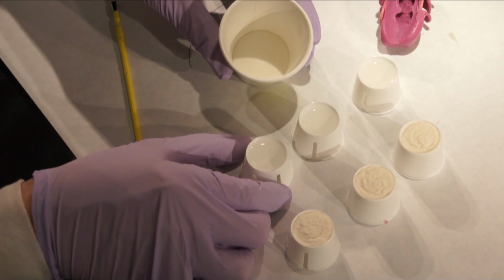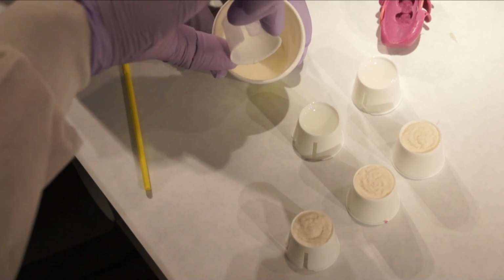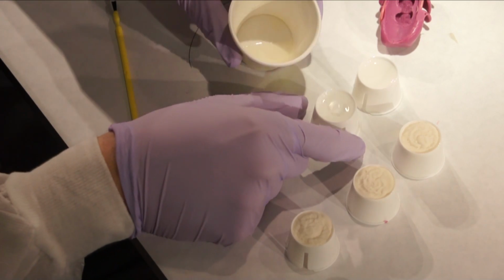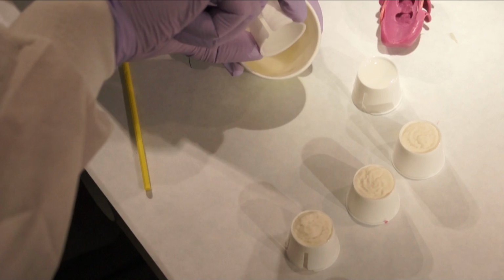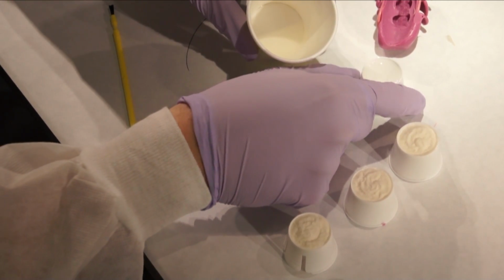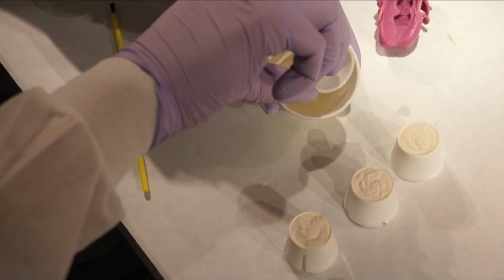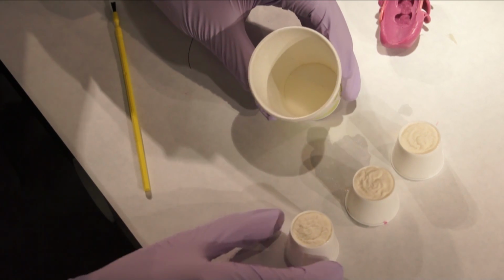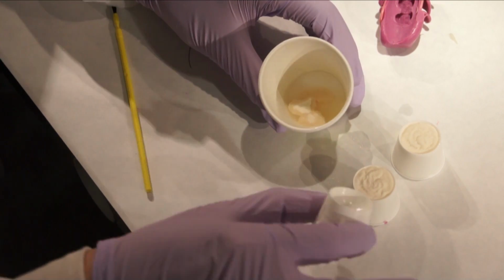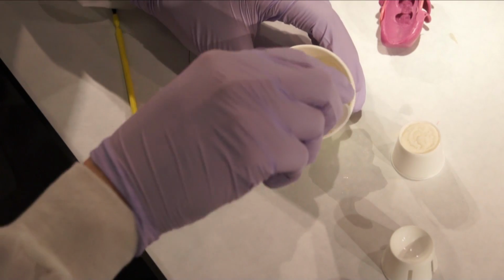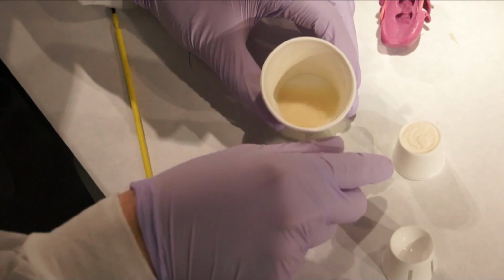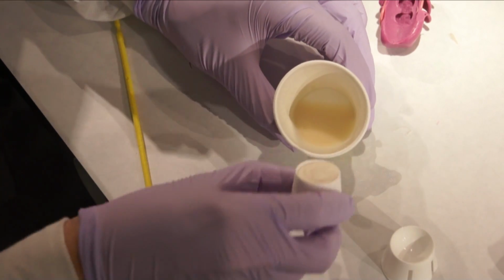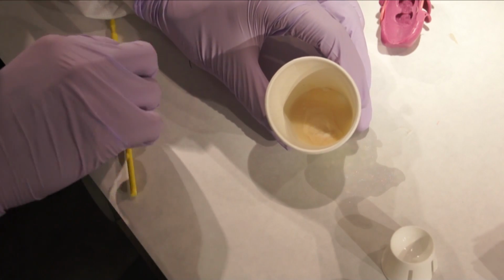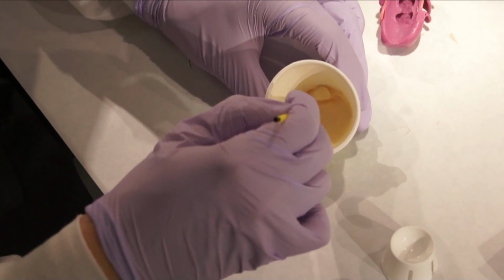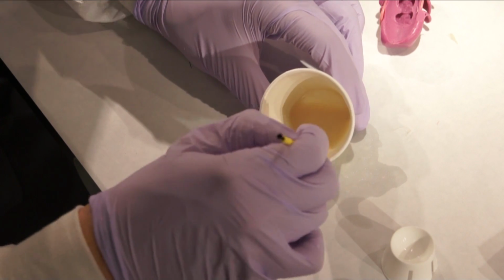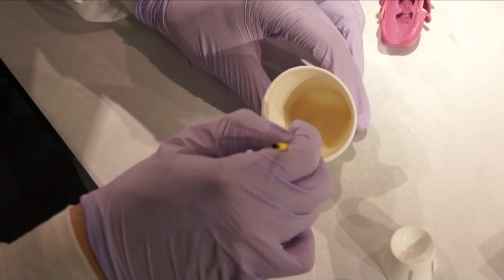The polymethyl methacrylate, PMMA powder, is added to the methyl methacrylate liquid monomer. The ratio is approximately 1:1 powder to liquid by volume. The mixing time should be approximately 30 seconds. Initially, the material is quite runny, but after about 1 minute, it becomes sufficiently viscous to easily manipulate. The material is poured into the putty matrix in the region of the planned provisional FPD. This procedure is done slowly in order to minimize air entrapment in the acrylic resin.